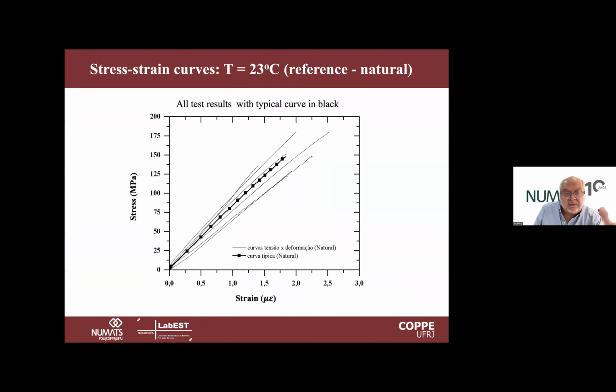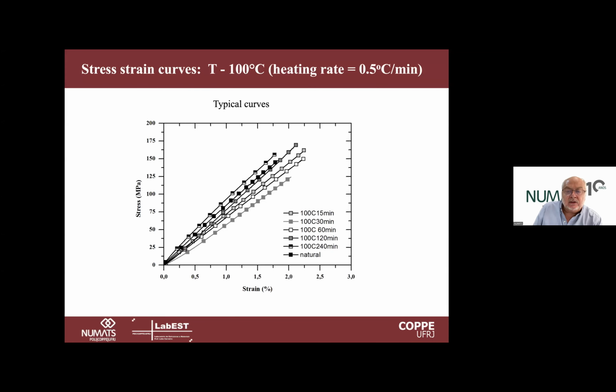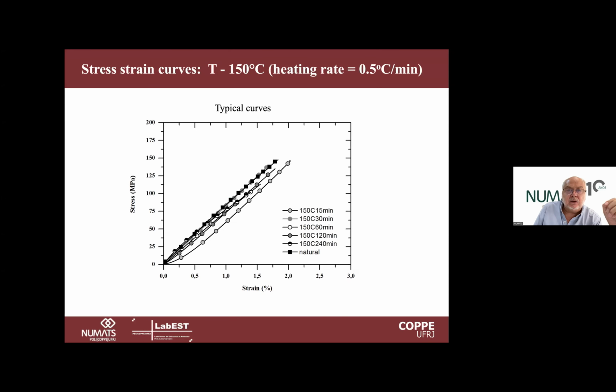So these are the variables, it's 5 curves. The one in black is the typical response. So this is the non-heated sample, the reference one. When we increase the residence time at 100 C, it only dries better, so it doesn't change much. It even increases a little bit the elastic modulus of the material. But when we go to 150, up to 150, this is a benefit. We have benefits from this behavior.